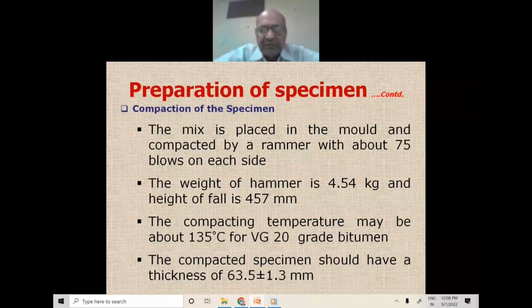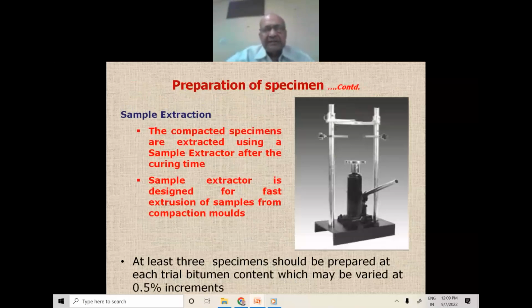First, we will prepare the specimen for optimum bitumen content, and the coarse aggregate, fine aggregate, and the filler material should be proportioned and mixed as per the dry mix design. Required quantity of the dry mix is then taken so as to produce compacted bituminous specimen of thickness 63.5 mm approximately. 1100 gram of the aggregate and the filler is taken to get the standard specimen.